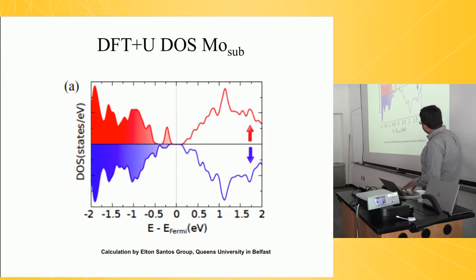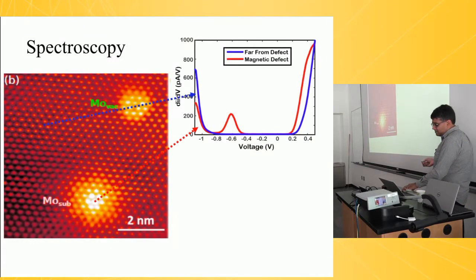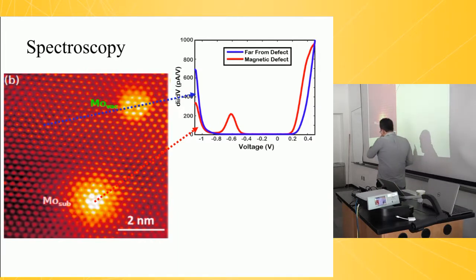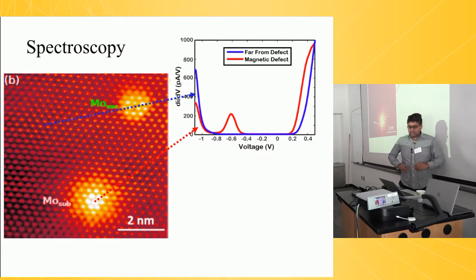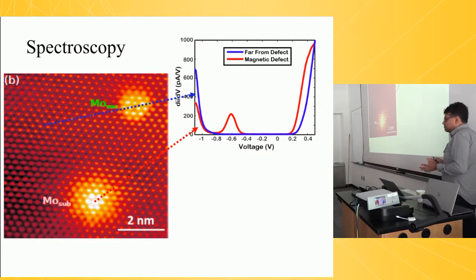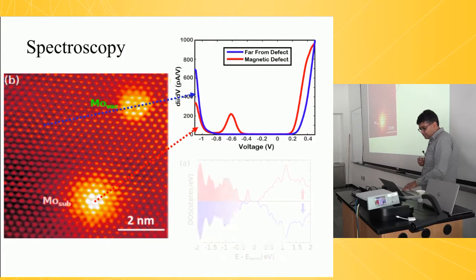We talked to a theoretical collaborator, Elton Santos at Queen's University, and he simulated this antisite defect. He seemed to think that this thing would be magnetic. And indeed, if you look at the spin polarized density of states associated with this defect, you saw some nice in-gap state, which in his calculations was magnetic. So we went hunting for this particular defect state, and voila, we saw a defect state. But in this STM, of course, we're not spin sensitive, and so I cannot say that there's anything to do with magnetism other than the fact that there's a state there.